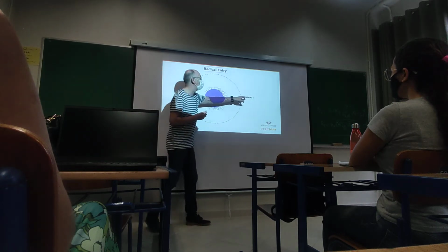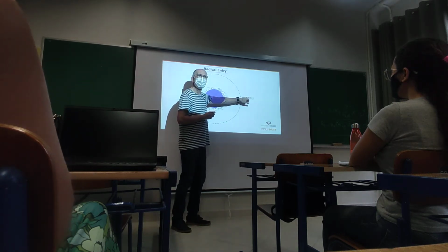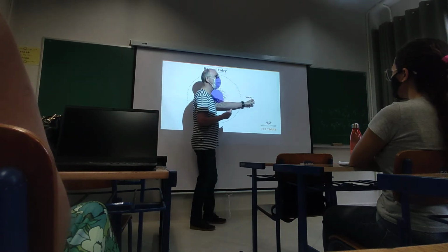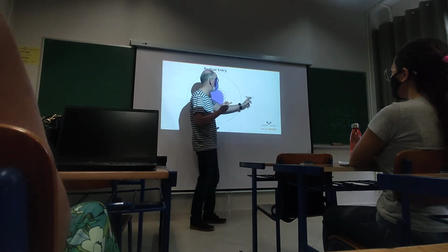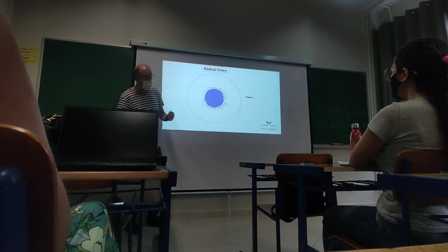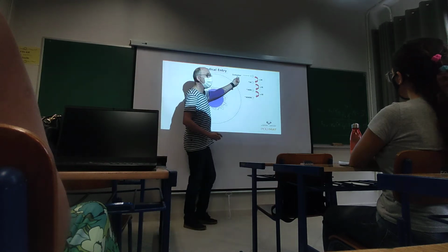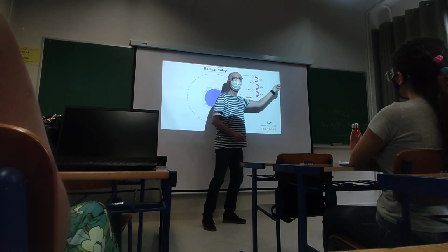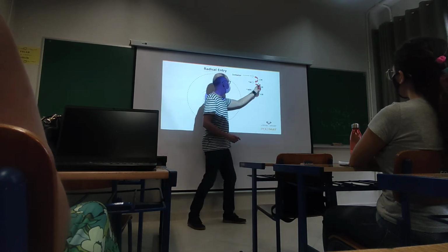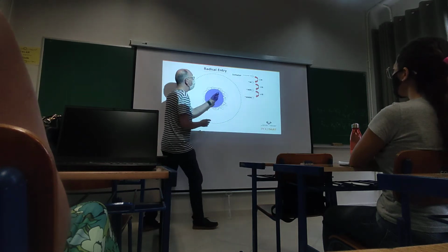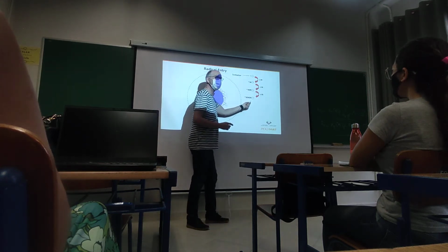But first we have to form this radical, which is surface active. That means that a radical to enter has to have, as we discussed yesterday, a few monomer units that make it surface active. From here we have to reach here. In between we might have termination reactions. Not all the radicals will reach this size, so only some radicals will enter.